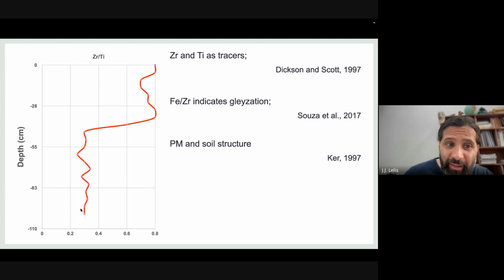So what can we say about the parent material of this specific soil using the zirconium-titanium ratio? This huge variation here, close, let's say, to 40 or 35 centimeters of thickness, shows us that this section of the soil below, let's say 35 centimeters to 100 centimeters, all the layers and horizons formed in this section of the soil, they are formed from one specific parent material. For example, a sandstone. And all this area is formed by a second parent material, by another rock, or by another material. Why? Because the ratio between zirconium and titanium is quite different.